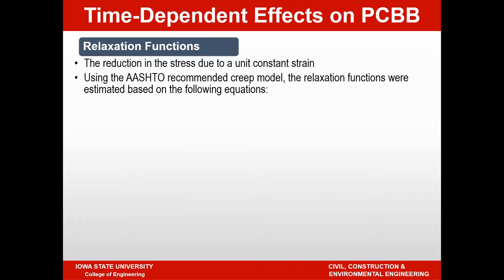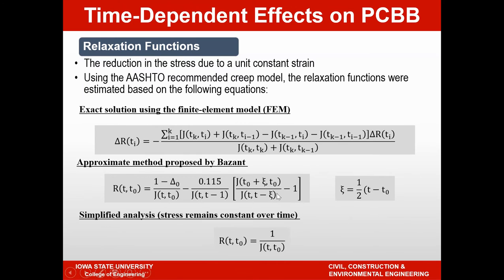So the relaxation function can be generated to capture the reduction in stress due to a unit constant strain. You can use, for example, the AASHTO recommended creep model, from which you can develop the relaxation function, and then that information can be established for a time step method as shown here, which will be required for performing a finite element analysis, and that's what we performed in MIDAS Civil. You could use an approximate method proposed by Bazant, or you could use a much simpler approach where you modify the modulus to represent the change in stresses because you're maintaining constant strain.